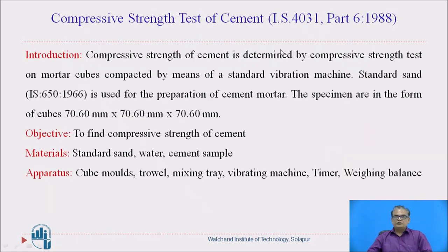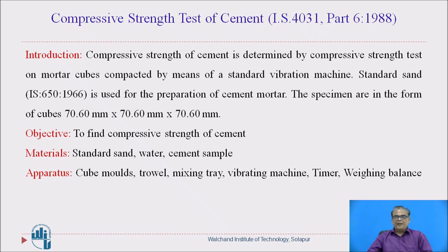Now let us see the compressive strength test of cement, which is performed as per IS 4031 Part 6, 1988. The compressive strength of cement is determined by taking the compressive strength test on mortar cubes compacted by means of a standard vibration machine. Standard sand as per IS 650:1966 is used for preparing these mortar cubes, and the size of the mortar cube is 70.6 mm.